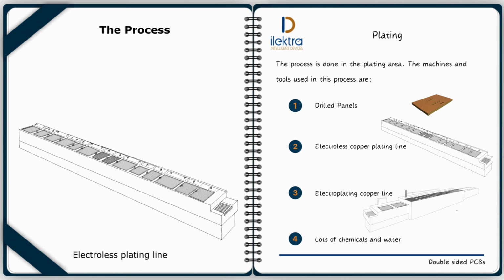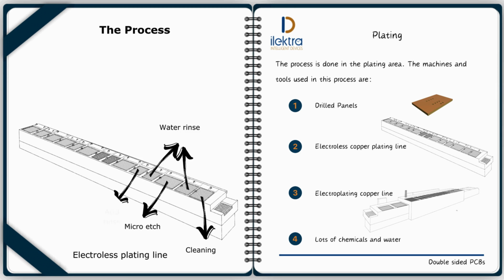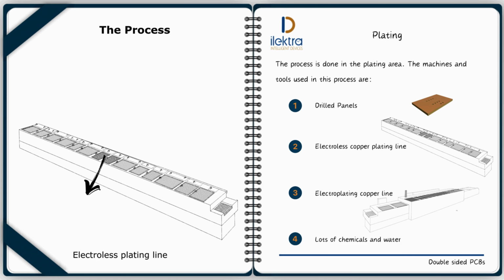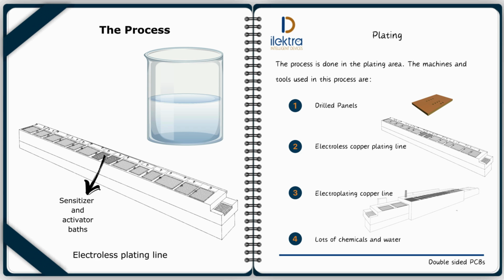Before all begin, the surface to be plated must be perfectly clean. The usual cleaning process of chemical clean, water rinse, micro-etch, water rinse, acid rinse and final water rinse is done to prepare the panels for the activation step. In the palladium stannous chloride catalyst system, the activation bath consists of palladium chloride and stannous chloride in hydrochloric acid solution. The stannous ions are absorbed by the surface of the dielectric material and reduce the palladium ions to atoms, forming the film on the surface.